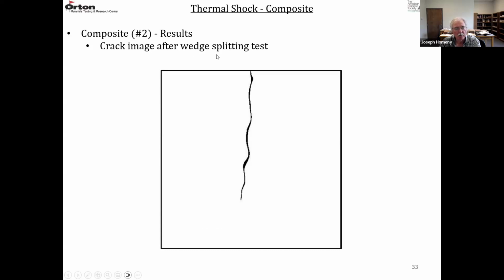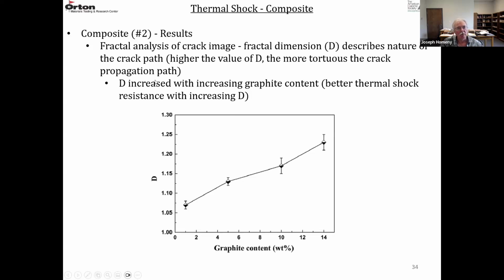So they took an image of this crack, its crack path, and they used a fractal analysis of that crack image. And they got a fractal dimension D. So that fractal dimension D describes the behavior or nature of that crack path. So the higher the value of this fractal dimension D, the more tortuous the crack propagation path.